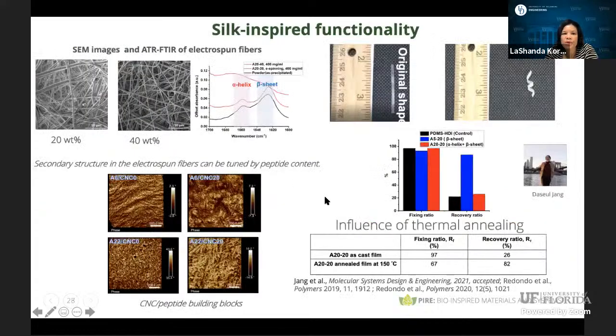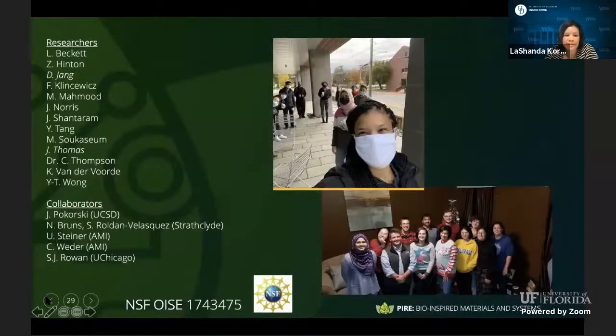Some other things that we are doing: I mentioned to you that we wanted to be able to make fibers from these, so we can show really nice electrospun fibers, and the fact that depending on the size and the composition, you have very different secondary structure conformations, which can be tuned by the peptide content. We're also making CNC peptide building blocks. The goal here is that we're now making water responsive shape memory materials.